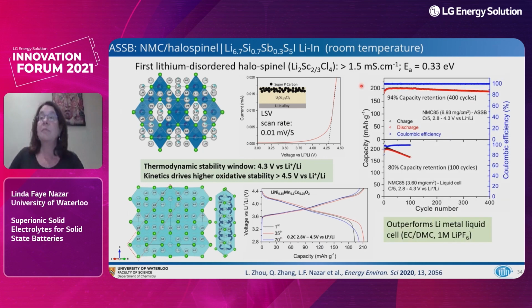We've explored this in much depth. I'll just give you a couple of highlights because I only have about 1 minute left. So this shows the data over 400 cycles of this cell. We have pretty much the standard capacity that you would see for NMC 85, even in a liquid cell. So this is the same, the liquid cell, just an EC DMC, 1 molar PF6. So we get the same capacity out of the solid state cell, excellent Coulombic efficiency, and the cell lasts for 400 cycles. And of course, the liquid electrolyte cell dies off because we're not using any fancy additive.